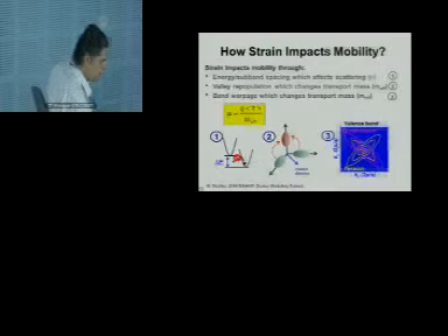However, for NMOS, what people do is deposit a nitride on the polysilicon. This deposited nitride on polysilicon produces a tensile strain. This is because of the dissimilar metallurgical properties. That means that tensile force is created over this region, and as a result, the electron mobility here is more than the normal without the silicon nitride. It is called a silicon nitride stress layer. This is the technology for NMOS. So PMOS with this kind of technology, and NMOS with this kind of technology. Let us not go into the details. We have very little time.